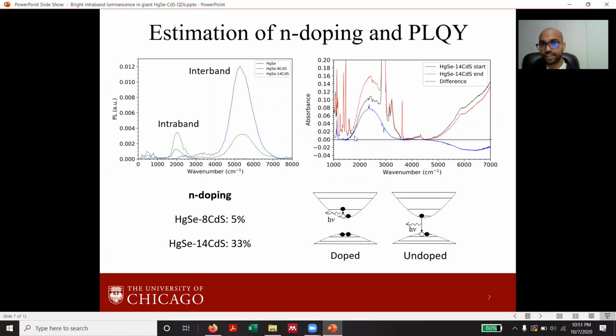The way we measure doping is shown over here. The black curve is the FTIR absorption of the 14 CdS dots using an in situ doping method, and subtracting the absorption spectra between the two samples, we get the change in the intraband absorption and an interband bleach due to the doping change. By taking a ratio of the peaks of the intraband absorption and the interband bleach, we can calculate the doping for a given FTIR spectrum of the core shells. Using this method, we have calculated the doping of the 8 CdS dots to be 5% and 14 CdS dots to be 33%.